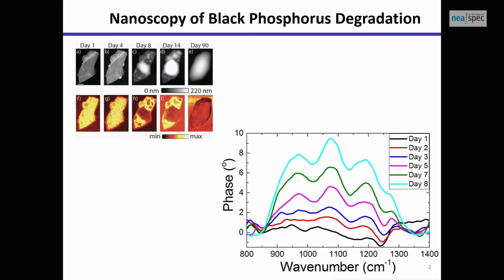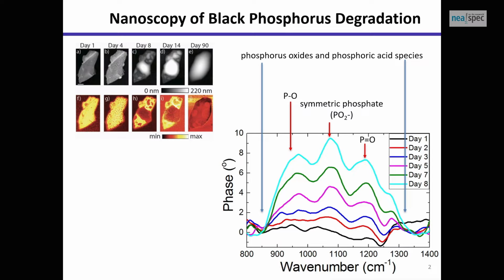This band, this range, is known to be phosphorus oxide and phosphoric acid species, and they have a vibrational response that you can map, and that's what you see here. The spectrum is quite broad, as there are so many overlapping modes in this range, but it's pretty much phosphorus and oxygen stretch modes. You can tentatively assign them as the P-O single bond stretch mode, the P=O double bond, as well as this symmetric phosphate mode that you see. So oxygen plays a major role. That's the take-home message. The reaction rate is determined by how much water and oxygen you have around this material, and it's quite complex. But you understand that water and oxygen are important for this material to fall apart.